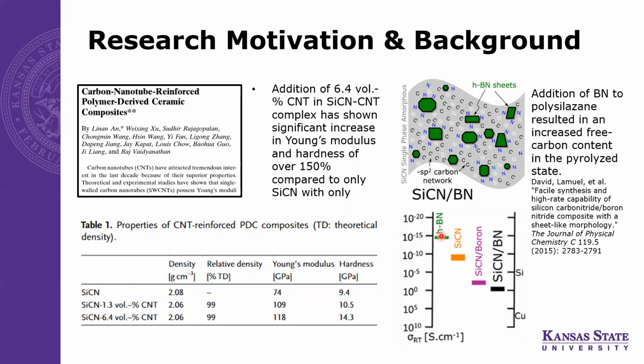Finally, in another study, sheet-like hexagonal boron nitride was chemically integrated with polymer-derived ceramic, specifically silicon carbonitride, via a simple pyrolysis route. This study suggested that a moderate amount of nanosheet material showed improvements in electrical conductivity, which is as high as doped silicon, but lower than reduced graphene oxide. Furthermore, an increase in electrochemical performance was also observed.